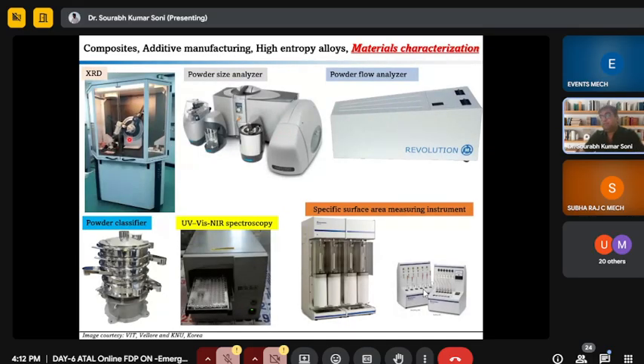So for upcoming researchers or very new participants, that's why I kept this PPT in my presentation. This is the XRD machine, so you can be familiar with the machine. This is the powder size analyzer, so you can analyze the powder size. This is the powder flow analyzer. After fabricating the powder through gas atomization or water atomization, you can analyze the powder flow through this machine. This is the powder classifier. If you want to classify the powder according to size, like 15 micrometer, 100 micrometer, 150 micrometer, or in the range of 100 to 200 micrometer, you can use this powder classifier.